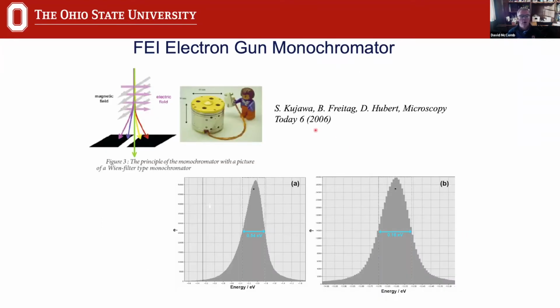And one of the first commercial electron monochromators was the FEI monochromator. We got a little Lego man or Lego person to show us the scale here that the monochromator sits in the gun. It's about 50 millimeters high. And it's effectively a Wien filter type monochromator. And with a Schottky type source, it would take our beam from an energy spread of about 0.5 to 0.6 electron volts to an energy spread of under 0.2 electron volts.